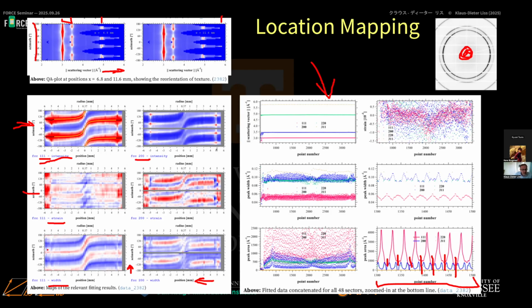So we can estimate which slip systems were activated there. For strain, we look to the residual stress in the material. So this is residual stress. It's not intergranular stress. Residual stress, which is orientation dependent. And we see it follows this S-shaped line where it reorients. Moreover, the full width half maximum, so that's not astonishing, right? What I said now. But what many people don't look at is the full width half maximum. So the peak width also depends very much on the orientation. And you may know people, they do Williamson-Hall plots and all these kind of things, where they look either into one orientation here on the XRD machine or many of the neutron diffractometers.